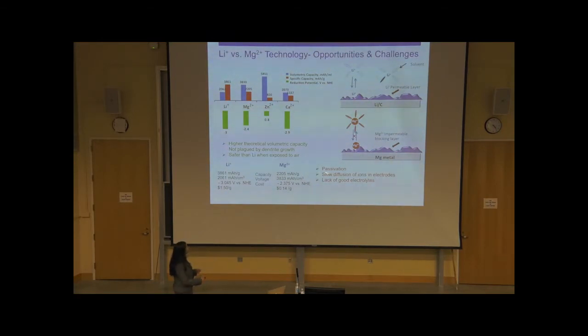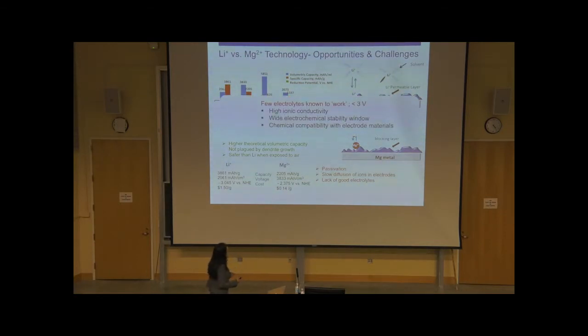The second problem is the slow diffusion of ions. Because of the +2 charge of magnesium, it forms a very rigid solvation structure, because of which the diffusion of ions inside the electrode material is extremely slow. So currently, we don't have any good electrolytes for magnesium batteries. There's nothing that can work for more than 3 volts. And if we want to commercialize these magnesium batteries, we need electrolytes with much higher ionic conductivity, a wide electrochemical stability window, and chemical compatibility with the electrode materials that we are using.